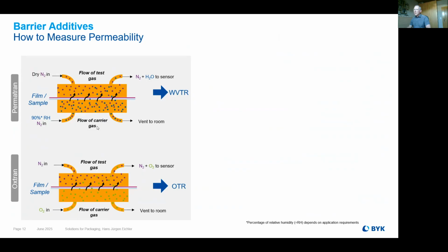a simplified working mechanism of the equipment which is used to check the barrier properties. You have the film inside. You have the flow of the carrier gas, and you are looking at what is passing by the film. The water vapor is taken with the flowing gas into the sensor, and then it measures the water vapor transmission rate. Something similar applies for the oxygen transmission rate. The carrier gas is again nitrogen, and oxygen is measured for that part. So with this equipment, if you have bought one, it's not possible to change it to other gases. It's really focused on what you bought, meaning water vapor transmission rate or oxygen transmission rate.